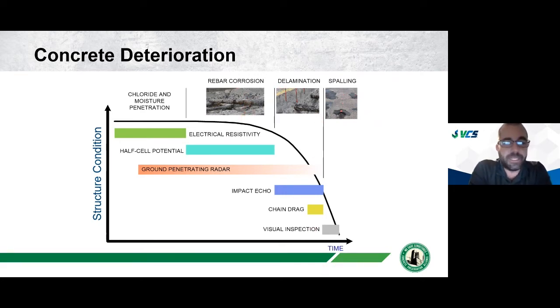In addition, as I showed earlier, all of these conditions are happening simultaneously on a structure. If you see a spall in one location, there's guaranteed to be some delamination in another area. And in another area, there's going to be rebar corrosion that hasn't created the delamination. And maybe there's areas where just chlorides are starting to build up. So on any existing structure that's been in service for any number of years, you're going to get all of these condition states happening simultaneously. If you're going to properly understand that structure, you should really identify where these things are occurring on that structure. And there are different tools that can be used to identify that.